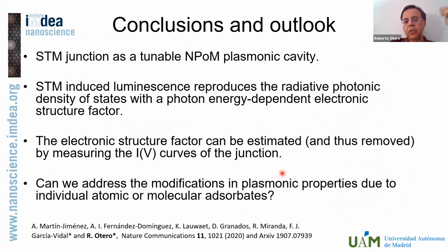So with all this, I think that we have shown, first of all, that indeed an STM junction is very similar to a tunable nanoparticle on a metal plasmonic cavity. That what STM actually measures is the radiative contribution to the photonic density of states in the plasmonic gap. We have shown how the actual spectra is composed of 2 different factors, a factor containing information about the electronic structure and a factor containing information only about the optical properties. Therefore, we can remove the influence of the electronic properties and be left only with the optical properties.